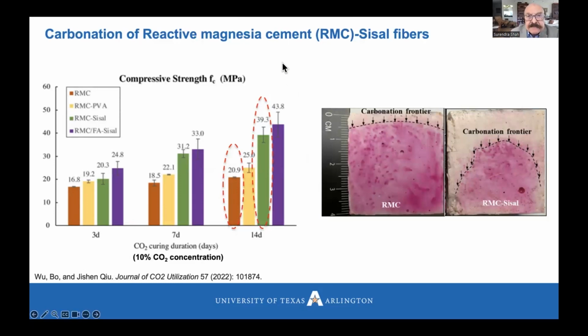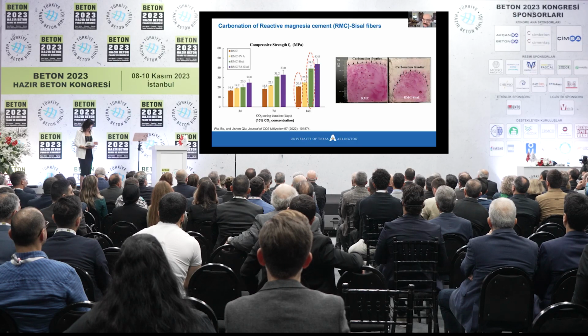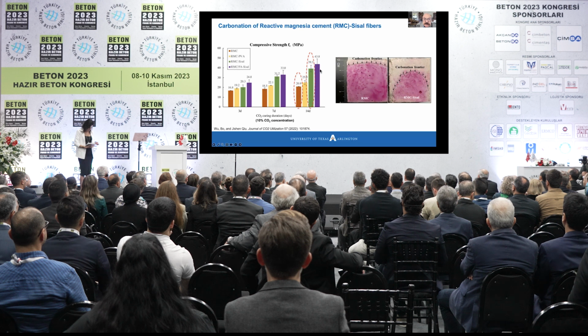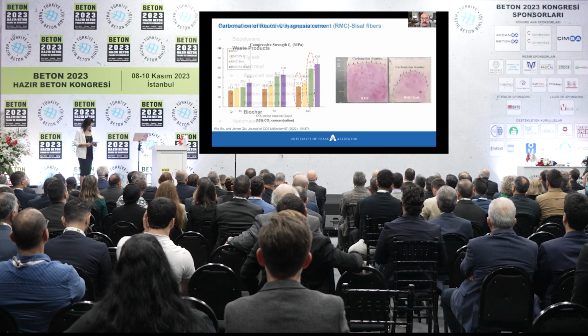An example of this is a sisal fiber work done at Hong Kong University of Science and Technology, where they took MgO or reactive magnesia cement to replace Portland cement. And they carbonated it without sisal fiber and with sisal fiber. And you can see that with sisal fiber, you can increase the amount of carbonation quite a bit. And this is also shown here with 14-day compressive strength of this is a controlled reactive magnesia, and this is with the addition of sisal fibers. So natural fibers can, as I said, act in multiple ways.